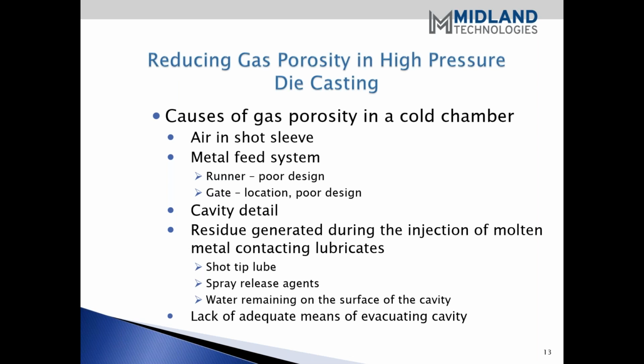So the causes of gas porosity. The number one, it begins with the cold. If we just take the different components in the shot system and injection system, it is air in the shot sleeve itself remaining there. The metal feed system, the runner, if it's not properly designed, the gating, and also location can be a contributor to gas porosity. The cavity detail itself, and of course, with the cavity detail, there's not much we can do with the detail that's in the cavity, because that's one of the fixed items that we have. There are some things we can do with the design of the part that may help us reduce porosity, but as a general rule, we've got what we've got.